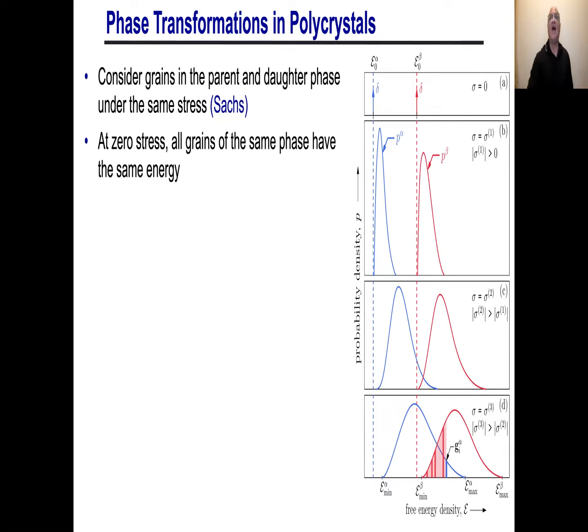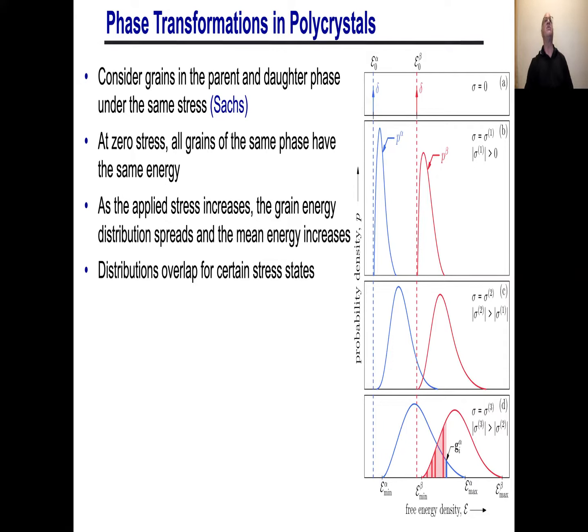Okay. Now, if I increase the stress monotonically, I just take whatever stress tensor I'm applying and increase its magnitude, what's going to happen is these distributions are all going to shift to higher energy. So the mean will shift to higher energy and the distributions will broaden. So that's what we show here: at zero stress, all grains have the same energy in the same phase. And as you apply larger and larger stresses, distributions shift to higher energy density, and also the width of the distributions increases.